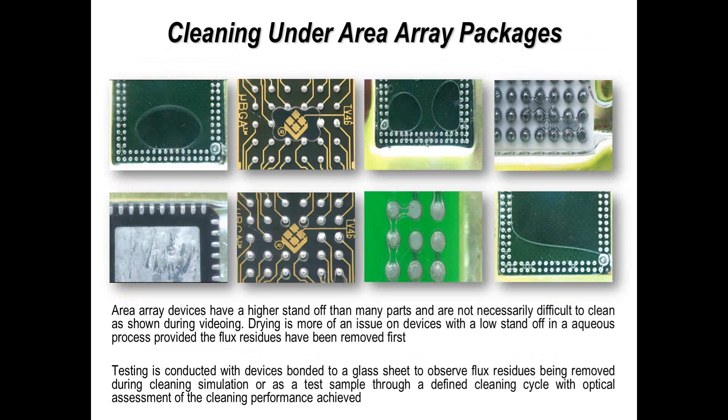The same type of test can be conducted with area array packages using the actual package, because components with solder joints do affect the way the cleaner runs underneath the package. With standoff heights of six thousandths of an inch and above, you really shouldn't have any problems. For BGAs of this sort of standoff, it's simply not an issue. As you get below four thousandths of an inch, it may start to be a factor, but with today's technology, even with fine-pitch BGA, it should not be an issue.